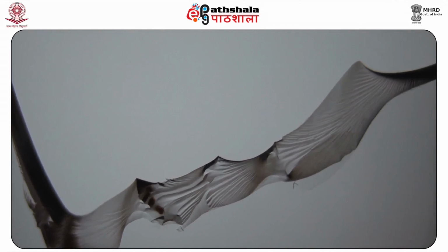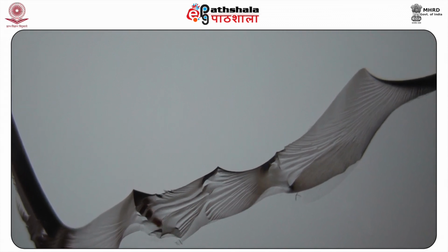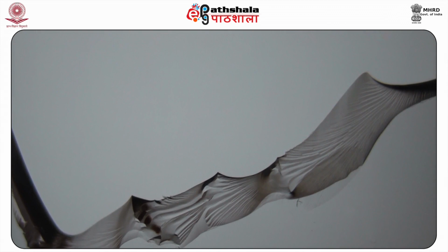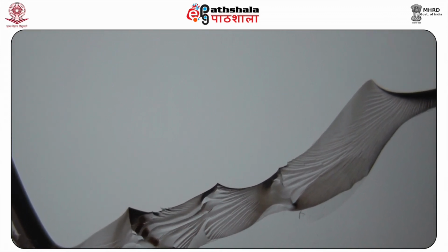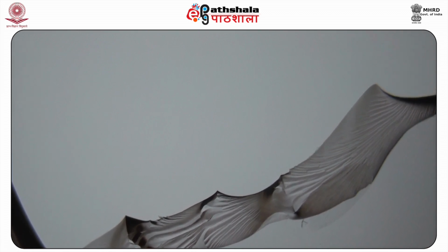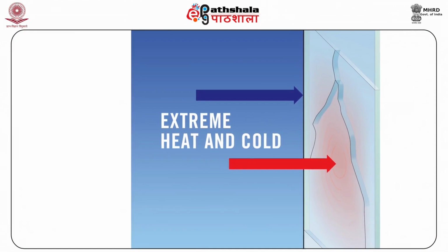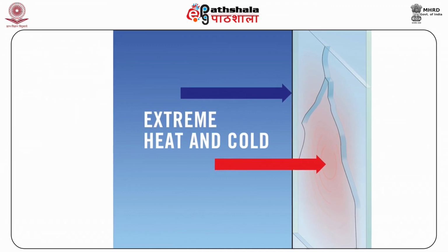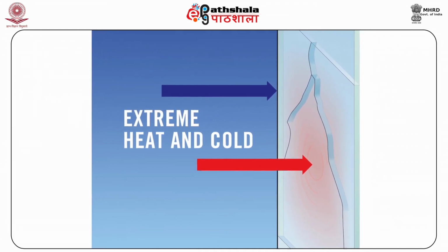Internal pressure. If a glass container fails due to excessive internal pressure, the typical fracture appearance is a straight, vertical split in the sidewall of the container, which may result from excessive carbon dioxide in beverages, from thermal expansion of liquids due to heat, or generation of gas due to decomposition of contents.